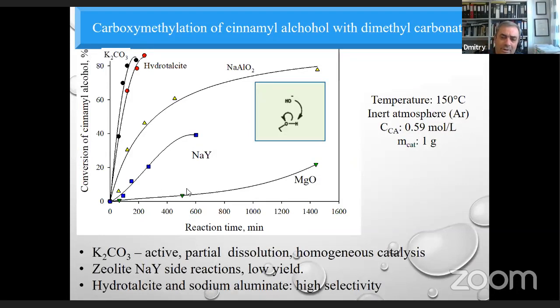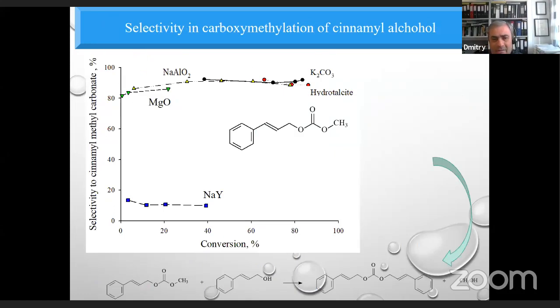What we tested, MgO was not very efficient. Sodium aluminate was more active than magnesia. Hydrotalcite was rather efficient, even high selectivity and high activity, and the efficiency of hydrotalcite was very close to activity of potassium carbonate, which dissolved not completely, but partially dissolved, maybe by 80% or something like that. So clearly, in the case of potassium carbonate, we have homogeneous catalysis. The selectivity towards the desired product was rather high, approximately 80–90%, independent on whatever it is, homogeneous or heterogeneous catalysis.